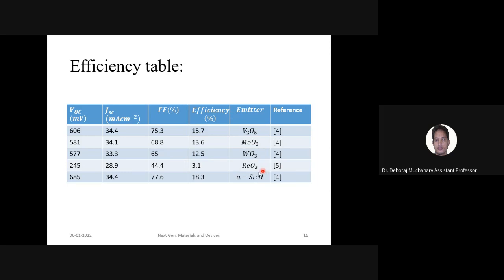And ReO3. These four materials were compared, and it is found that with V2O5, it's showing a VOC of around 606 millivolt. Up to that much VOC they are getting. The short circuit current density is also good, around 34.4 milliampere per centimeter square. Another one is the fill factor, which is around 75.3%, and the efficiency is 15.7%. If you see in this table these four different transition metals and the corresponding efficiency, the least one is due to ReO3, with an efficiency of around 3.1%.